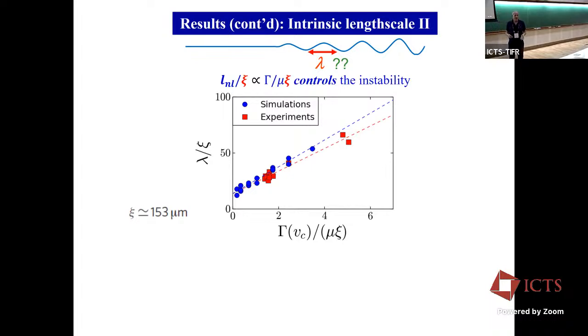And it didn't matter. The only thing that mattered in these simulations was the fact that there was a nonlinear scale in the system. So you have either softening or hardening, but you still get the oscillations for the same reasons.